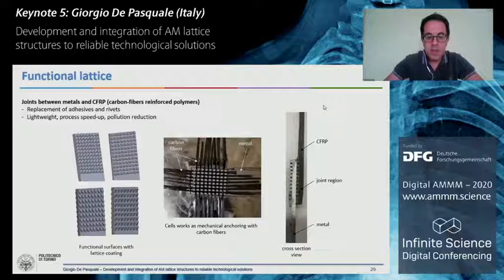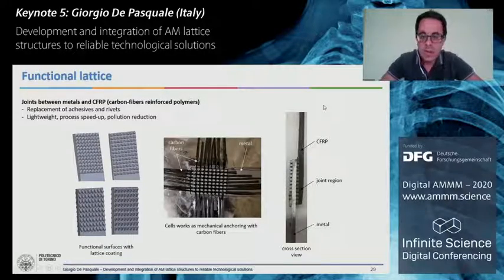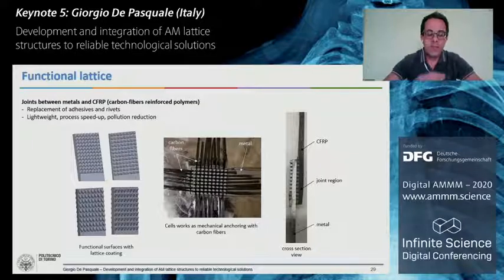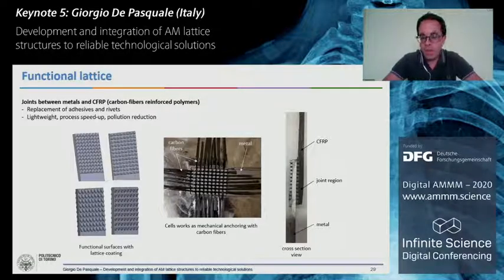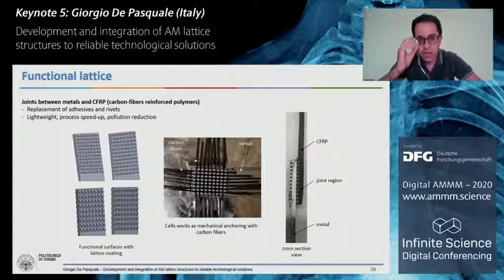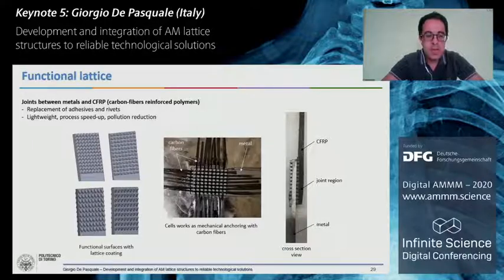The very last thing is the functionalization of lattice structures. In this case, we are using a coating of our metal parts that is based on a lattice coating, to create a smart joint with carbon fibers polymers, so with composite polymers based on carbon fibers. We provide a mechanical connection between the carbon fibers and the lattice cells in order to improve the adhesion of the two materials to create a functional joint without adhesives or rivets or mechanical connections. And this is very useful for lightweight applications. It's useful because it speeds up the process of joining metals and composite materials and reduces the pollution related to the adhesives and chemical agents used for the adhesion.